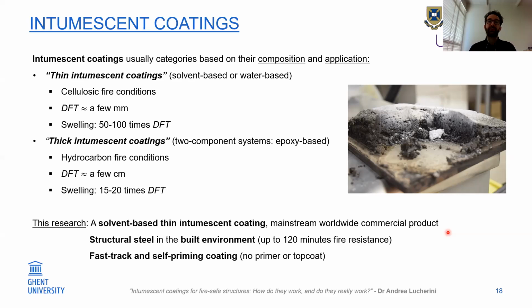For this specific research, I selected a solvent-based thin intumescent coating that is a mainstream worldwide commercial product, available in the market everywhere in the world. It's usually applied to structural steel in the built environment, and depending on the initial DFT and the size of the structural element, you can achieve up to 120 minutes of fire resistance. And it's a fast-track and self-priming coating, so no primer or top coat was required.